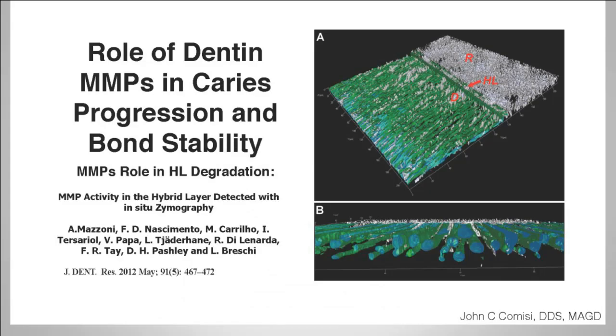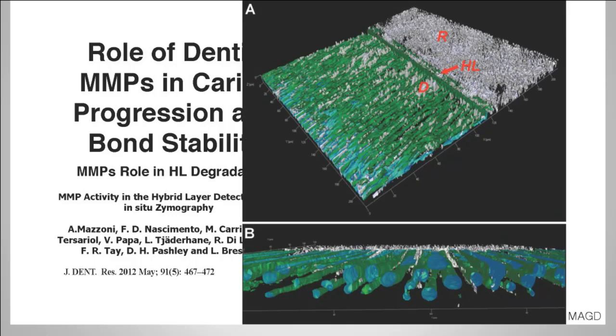of dental composites. In another paper by Annalisa and Breschi, they show this hybrid layer degradation in the zymograph, which is really fabulously illustrative. On the lower left side of the upper image, you see this green layer with the D, and then you see a line with an arrow pointing with HL. Well, the D is the dentin, and the HL line is the hybrid layer, and the R is the resin, as zymograph. The green represents the enzymatic breakdown that is occurring and the body's response to the hybrid layer.